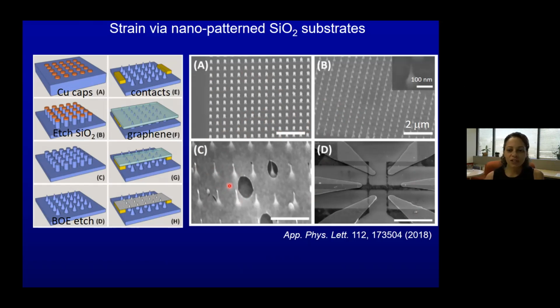Okay, and here we actually put a hole in here because we try to find regions that aren't ripped. Here I show a ripped region so you can see the contrast between this light gray, which is the suspended graphene, and the dark gray, which is the substrate. Right? And you can see very clearly that the graphene is mostly suspended on top of these pillars, okay, and then patterned here for measurements.